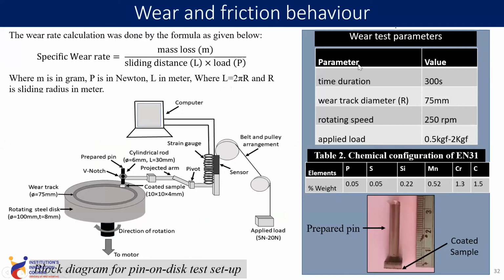Wear and friction behavior of the coating, the parameters that we are using. This is the setup that we are using, that is pin on disc test setup. The formula of specific wear rate: while calculating the weight loss, mass loss, sliding distance of the wear track and the load, we obtain the wear resistance.